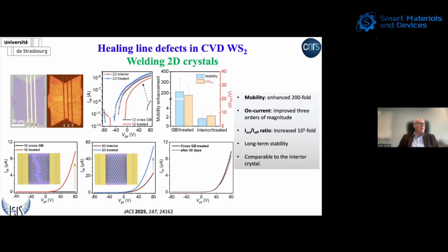What is quite striking is this example here, where you have the interdigitated electrodes, electrodes 1, 2, and 3. And we have a line defect between 1 and 2, and we have no line defect between 2 and 3. And therefore, upon healing, we can see a major increase when we measure the current passing between electrodes 1 and 2, as you can see from this curve to this curve here. Whereas when you are wiring up electrodes 2 and 3, upon the healing, you have a much more modest increase in the current through the junction. Okay, this kind of treatment lasts quite a long time, so it's quite robust.